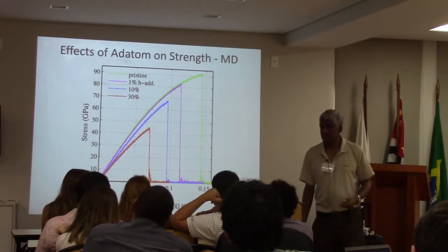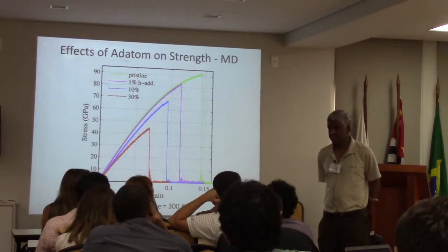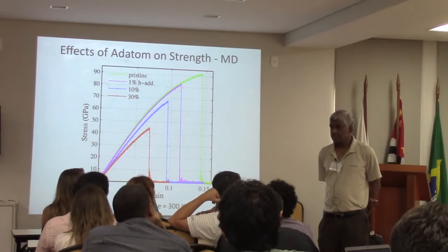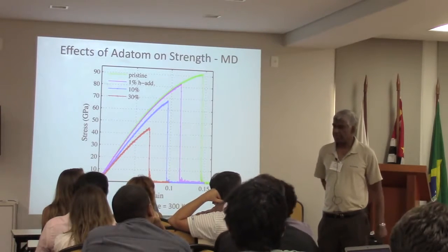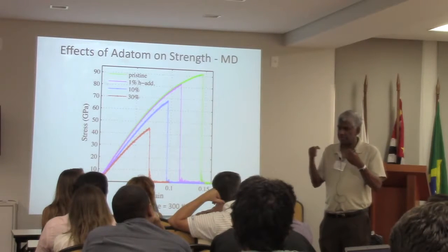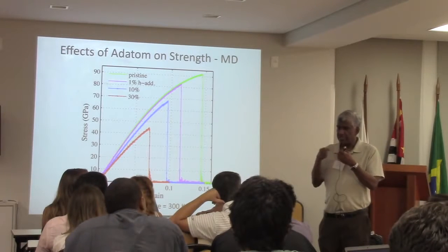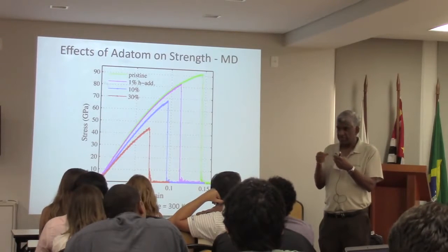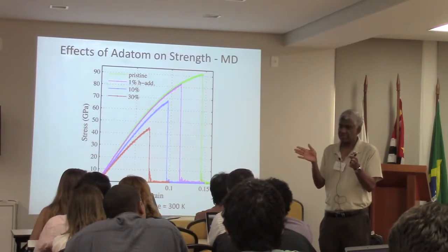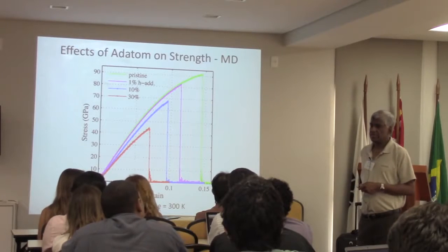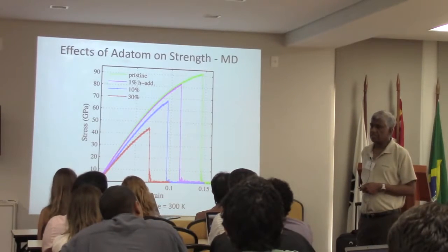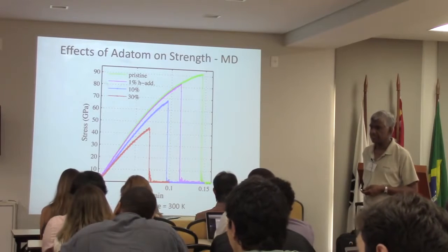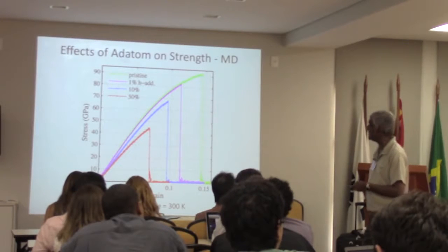The simulations we use, usually you cannot break a bond in any of these simulations, at least the ones we use. So how do you see the bond breaking process there? Is there QM involved, or a different potential function? There's a different potential function. The bond breaking is interpreted mainly in terms of the cutoff radius. If you take LAMMPS, you can see bond breaking, because the interaction between certain atoms no longer works. The potential does not have the quadratic bond terms. This is the ReaxFF potential, so the potentials are dissociative. Yes, it is a different potential function that we use.